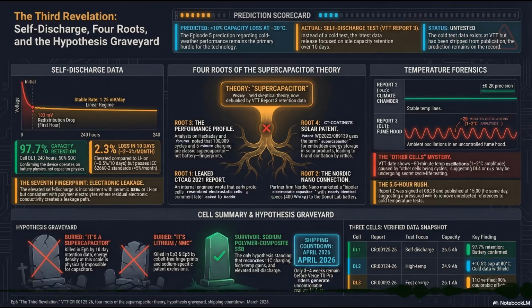It does, but we have to attach a massive, bold-faced caveat to this 2.3% figure. We do, because it is a best-case scenario caveat. Absolutely. We must remember that VTT tested this cell at exactly 50% state of charge. Resting at 3.7 volts. Half full. As we discussed with the water hose analogy, self-discharge is entirely dependent on voltage pressure. The higher the voltage, the stronger the driving force shoving those electrons through the microscopic leakage paths in the polymer. Right, at 50% SOC, sitting at a relaxed 3.7 volts, the pressure is relatively low.